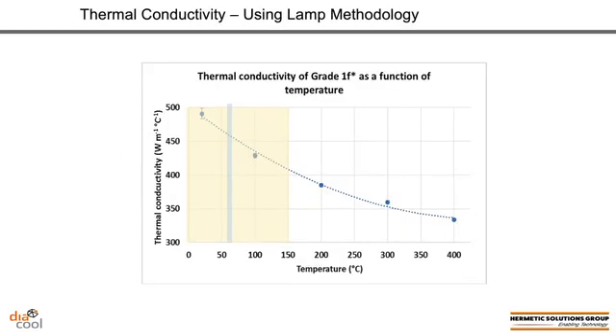So likewise, of course, I wanted to look at the thermal conductivity of this material. The chart you see here in front of you represents temperature range of essentially room temperature up to 400 degrees C. Again, that tan box represents typical operating temperatures of devices today. And you can see that this material has high thermal conductivity of around 415 watt per meter K up to about 480 watt per meter K in that operating temperature range.